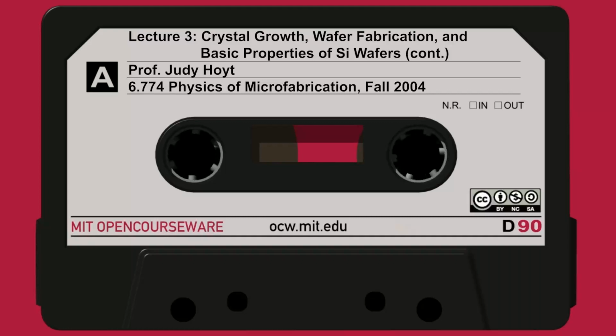The concentration of these defects is going to go up exponentially as I increase the temperature. In general, the equation at the bottom is true: the concentration of neutral interstitials in equilibrium is not necessarily equal to that of vacancies. It may be easier or harder to form, so don't think that they have to be equal to each other, because there are a lot of different ways to form these two different types of defects.